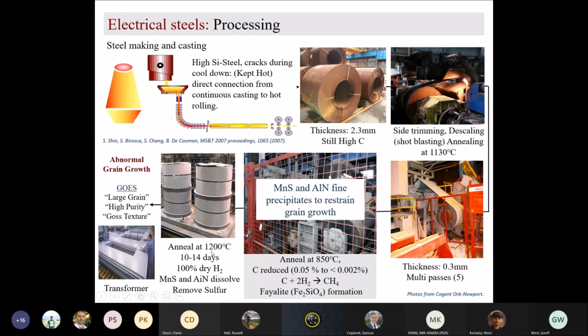So during the secondary annealing, not secondary recrystallization, that's the wrong word to use, because recrystallization is already partially or completely done during the primary annealing. So this is not secondary recrystallization as it is faultily named. This is secondary annealing, because the recrystallization actually happened previously. Now we are doing the grain growth.